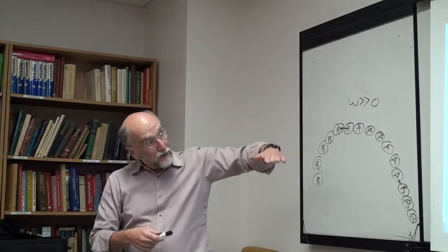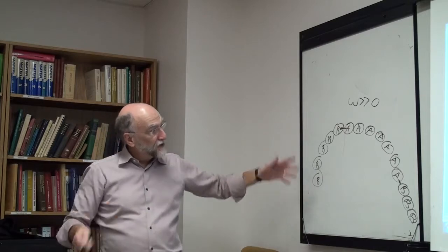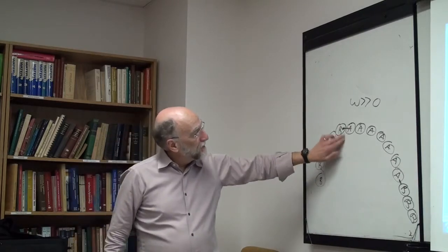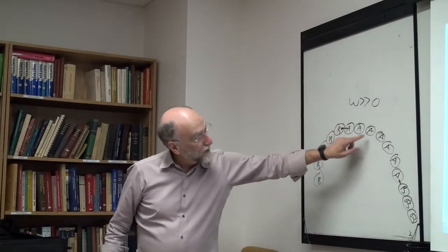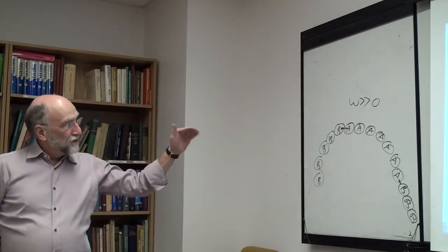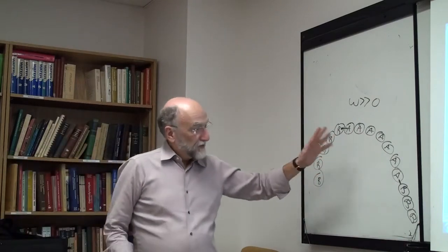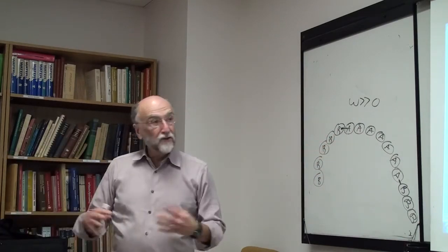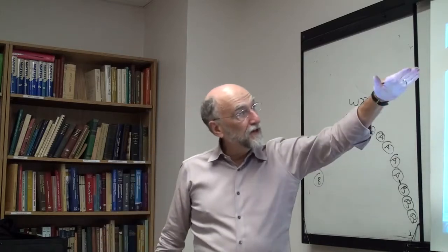The Gibbs energy just goes down smoothly like this. It never actually separates, because the number of AB bonds becomes very, very small. Only among the ends of these very long chains do you form these AB bonds, and these are not separate phases. They're just bigger and bigger clusters within one single phase, and there's never any tendency to split the thing up.